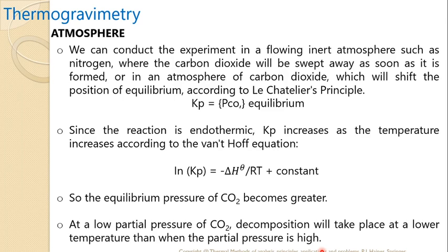Since the reaction is endothermic, Kp increases as the temperature increases according to the Van 't Hoff equation, that is ln Kp = -ΔH°/RT + constant. So the equilibrium pressure of CO2 becomes greater. At a low partial pressure of CO2, decomposition will take place at a lower temperature than when the partial pressure is high. So this is all about the apparatus with respect to the thermal analyzer, or the thermobalance. This is all about the instrumentation. Thank you.